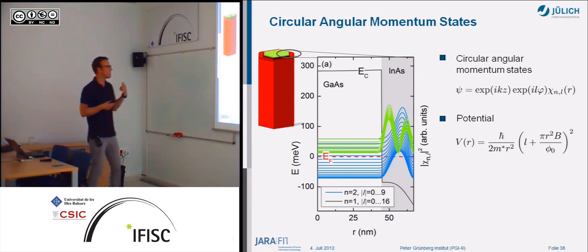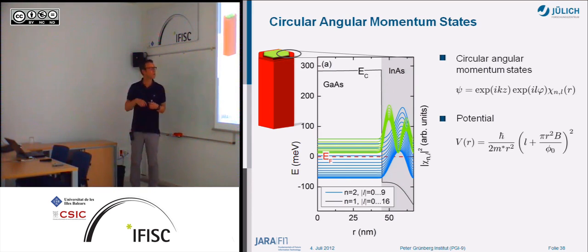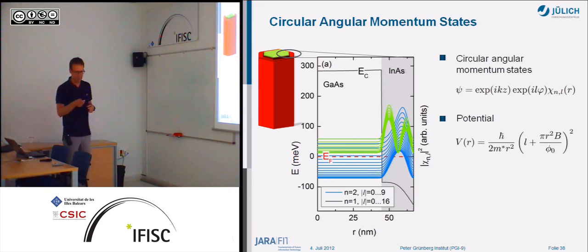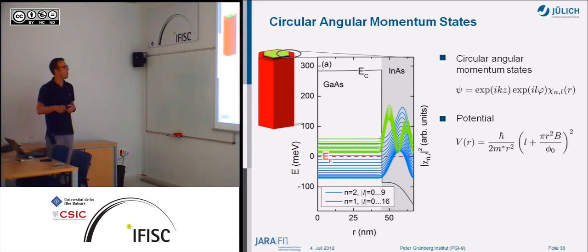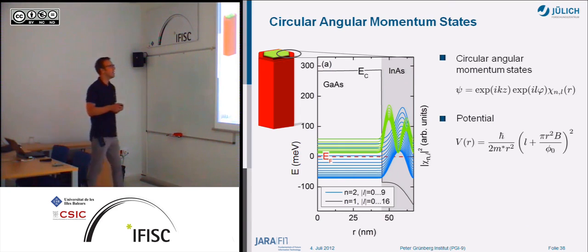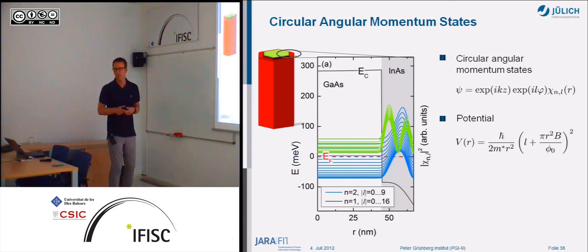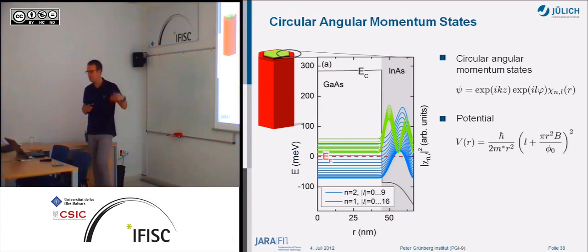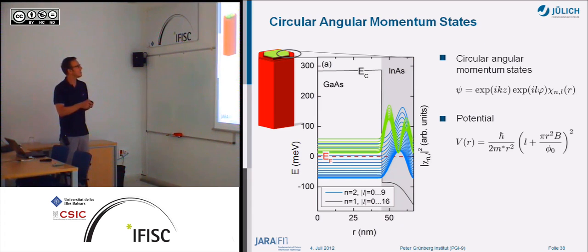So we rather think that this is not really due to some electron trajectories, but we're thinking of some angular momentum states which are responsible for this transport phenomenon. That's why we calculated the electronic states with a Schrödinger-Poisson solver. What you see here, this is gallium arsenide, this is the conduction band profile. We have a quantum well where the electrons are located inside the indium arsenide, and this is the surface of the nanowire. So you have a quantum well, but you have to think of having a circular state here. This is just a cross section, just a cut along this direction.